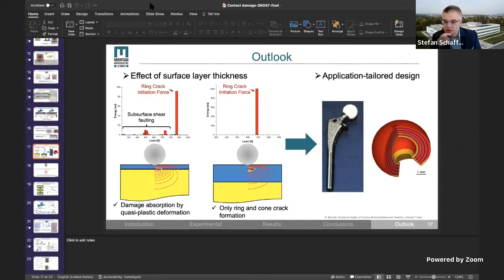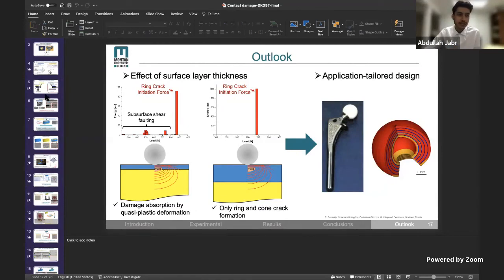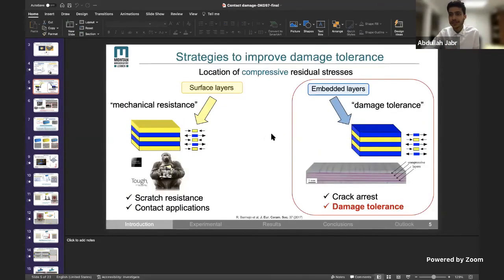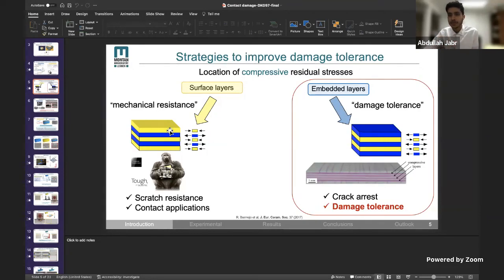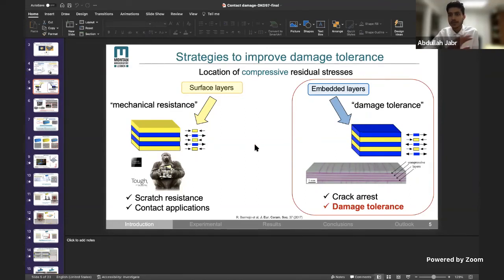If you would change the order of your material from ELE to LEL, would this have any significant effect? Yes, if we change the order, we will change our design to a surface layer design where we have the compressive residual stresses on the surface — this is also good. But if we initiate contact cracks, then our material will fail because we don't have any protective layers. This is the design used for Gorilla Glass — here we want to avoid crack formation. But in our design, we say it's okay to form cracks but we want to arrest these cracks. So these are two different approaches: it depends on the application, but we want to tolerate contact damage.